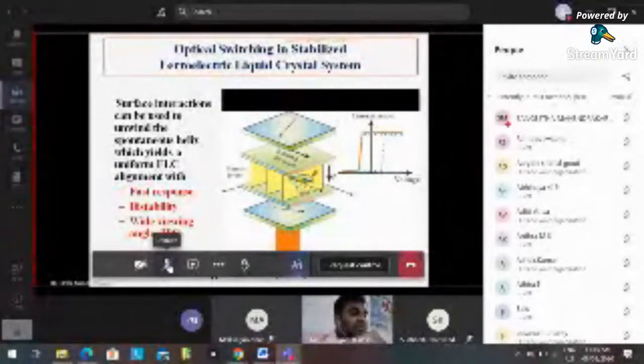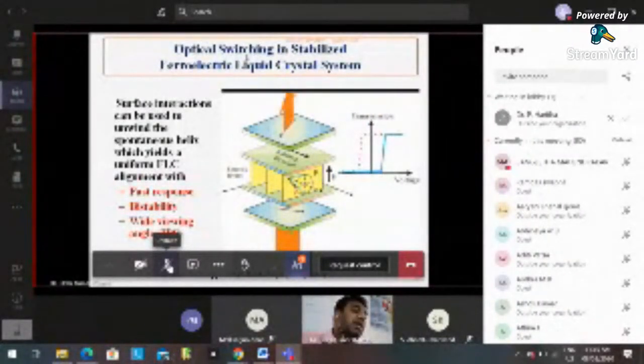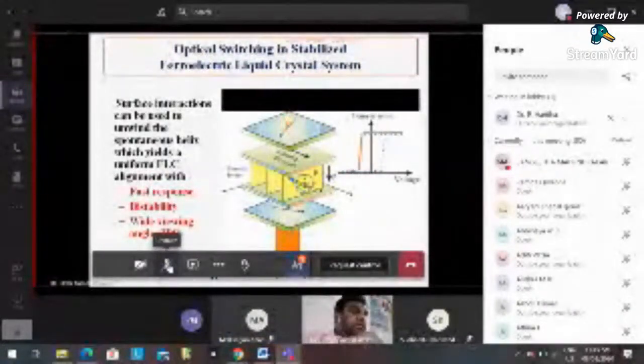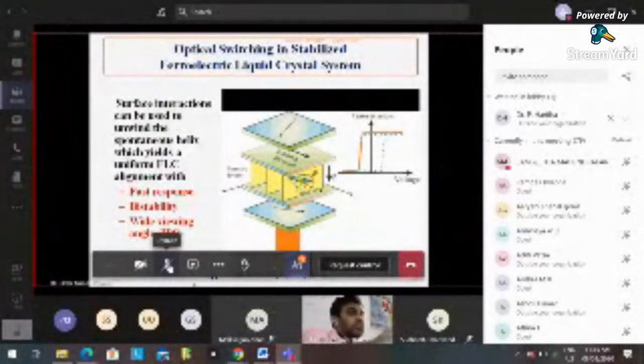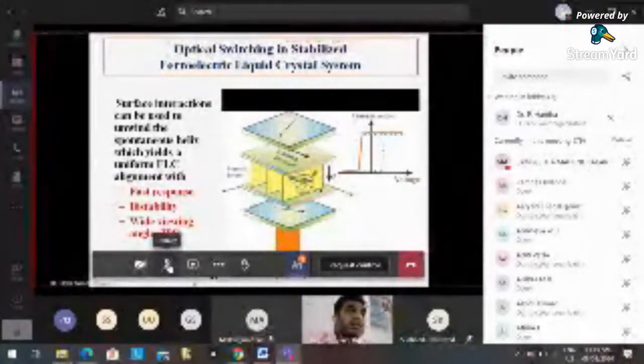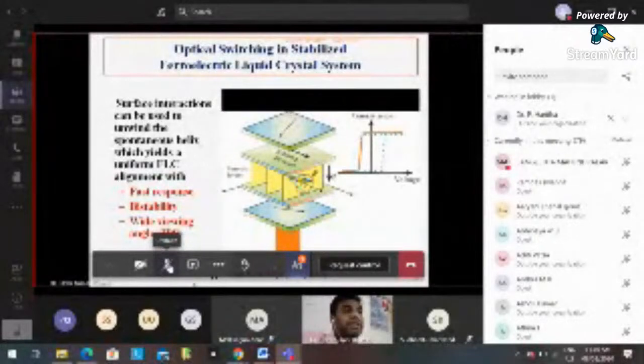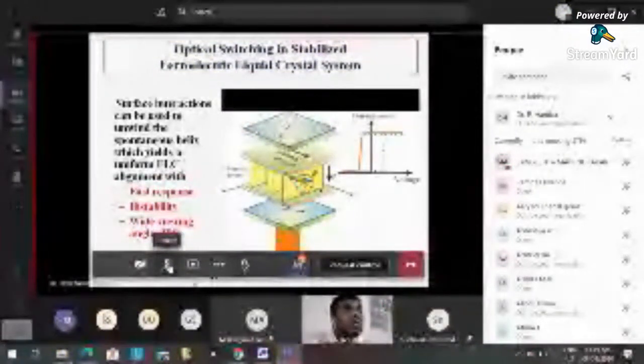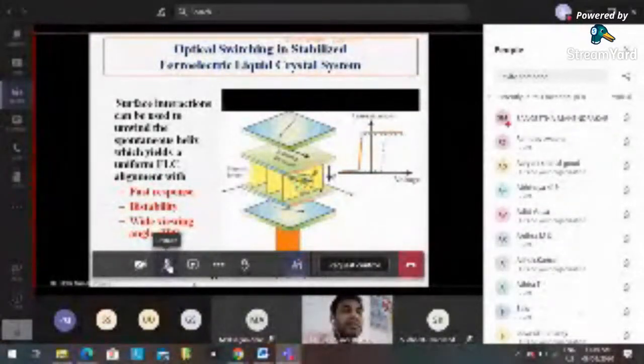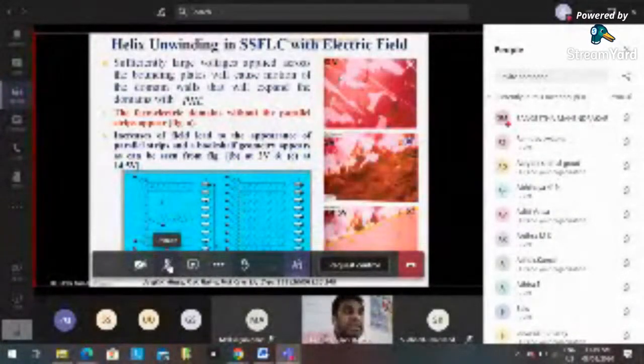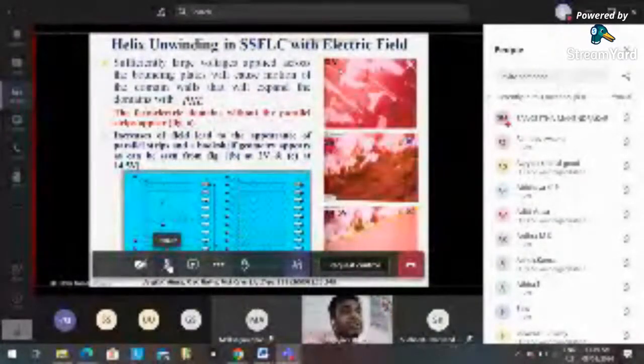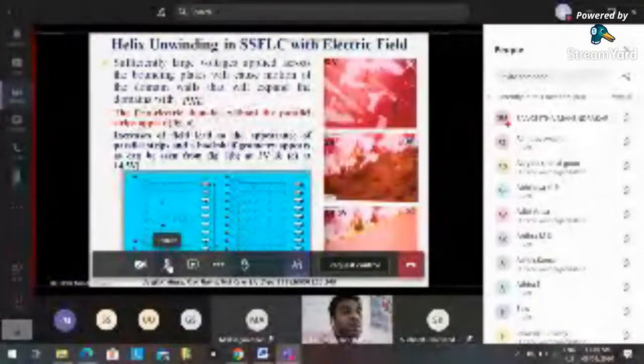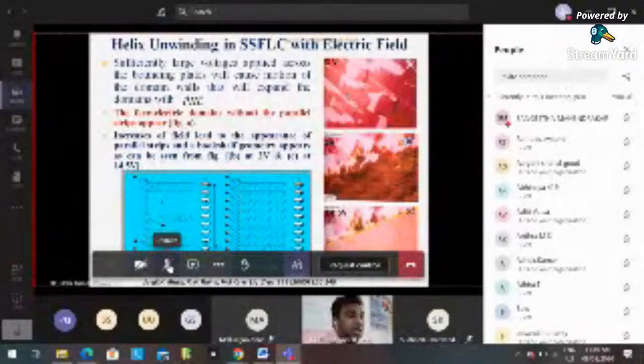That is useful for IPS displays. The first ferroelectric liquid crystal was discovered by N.A. Clark in 1980. So these are the different responses for surface stabilized ferroelectric liquid crystal materials. Here at the surface, some part of the texture is stabilized by the alignment, and this texture shows the stabilized texture, and there is a switching response at 0 volt. This type of behavior is there, but when we apply the field, the whole texture shows this, and this texture has been observed under the polarizer.